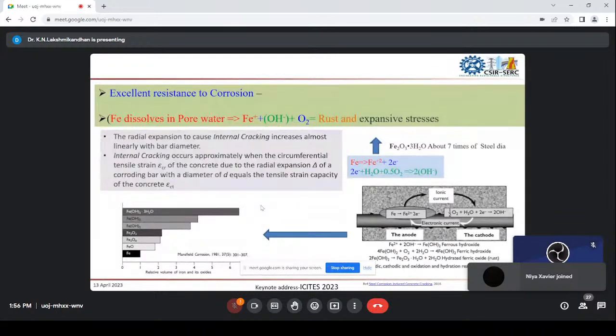Otherwise, it will break down. Once cracks are created in the concrete, they permit more water, that is H2O, and oxygen to enter the concrete medium. So it accelerates the corrosion. As a result, what we are seeing is very fast corrosion, and the life of the structure comes down. So these are the key factors we are seeing: how the cementitious compositions contribute to controlling durability, and also how, as a system, the steel can protect itself from corrosion.